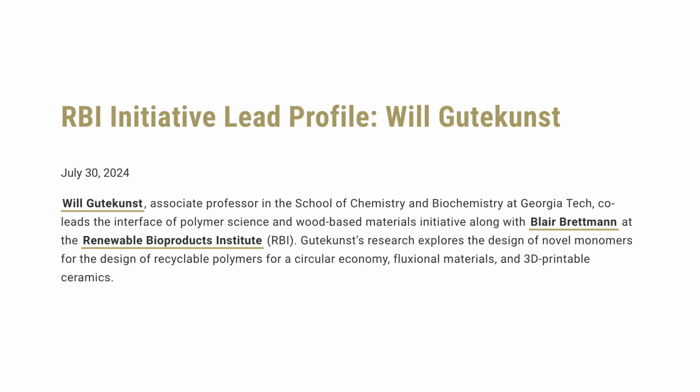In other projects, we do things that are kind of wild. We have a project right now trying to turn polymers, so soft materials, into ceramics. So these are polymers that, whenever you sinter them, so think about taking clay and putting it into a kiln and turning it into a ceramic, you can do the exact same thing with these soft polymers, and they turn into new high performance hard materials. The advantage of this is we can shape them and mold them beforehand, and we're even working on ways we can do 3D printing of these structures before we go and sinter them to the final ceramic product.